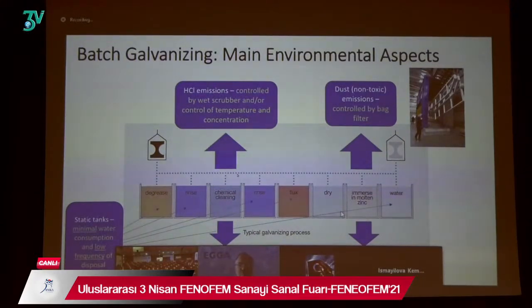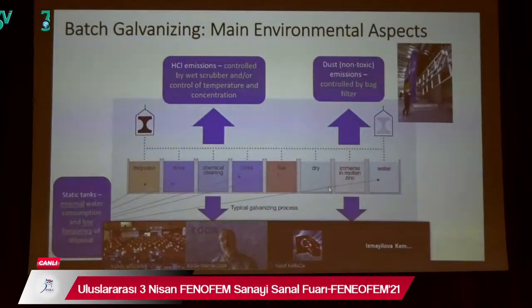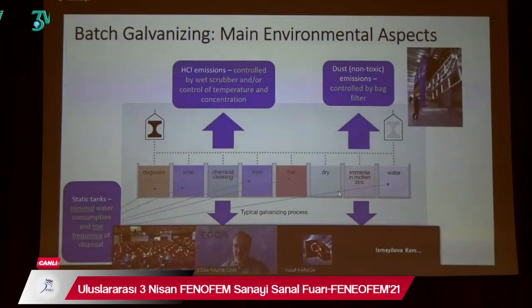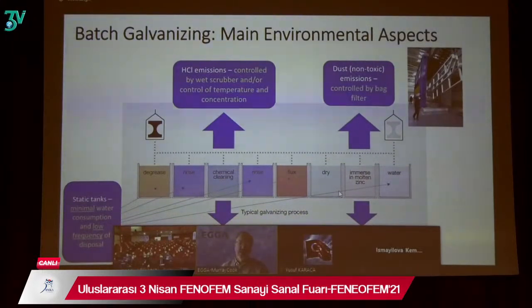So actually, from an environmental point of view, the process is very simple. We control the emissions from the hydrochloric acid by control of temperature and concentration, if not with a wet scrubber. Probably the biggest issue in our industry is disposal of the spent acid periodically, but we have a lot of ways of reducing the amount of spent acid we generate, but also hopefully we may have a market for recycling that acid. We control the particulate emissions with the bag filter, and our zinc wastes are actually recyclables, and there is a strong market for those.